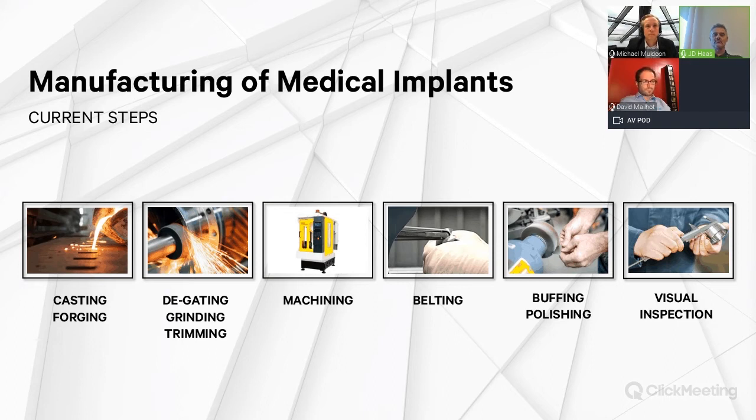And so the various parts of the knee, the knee isn't necessarily processed with just one belt. You have to have different sizes and shapes to get into all the little areas of the knee, the top, sides, and what we call the box area, very narrow file belts, that sort of thing. And so we step that down in this belting process. We'll use a sequence of what we call Trizact belts to take that all the way down to a pre-buff finish. And then some customers choose to do a one-step buff. Some customers will choose to do a two-step buff. But then it's a very short buffing process, and you've got your polished knee.